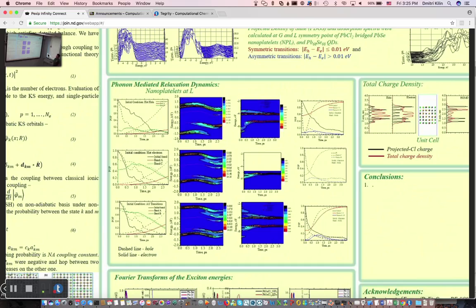And in this second scenario, this is for the hole transition with the hot electrons, so the electron energy is much higher. But if you compare the relaxation pathway of this electron and this hole here, this electron starts to relax after 1.5 picoseconds, and then relaxes to the intermediate band. It didn't relax to the frontal orbital. It's partially relaxed but not all. And we calculated this relaxation time up to 2.8 picoseconds. So it is still in the excited state, in the intermediate band.